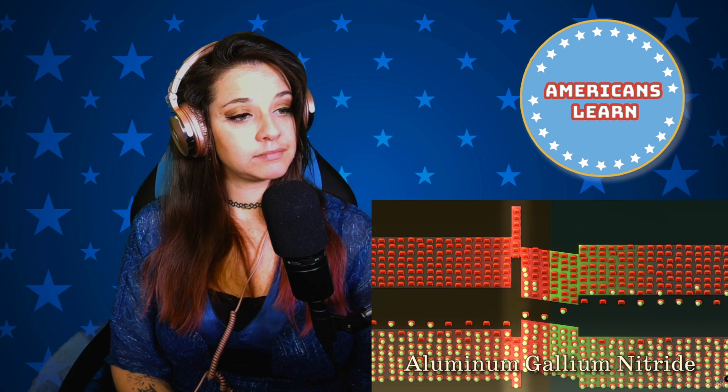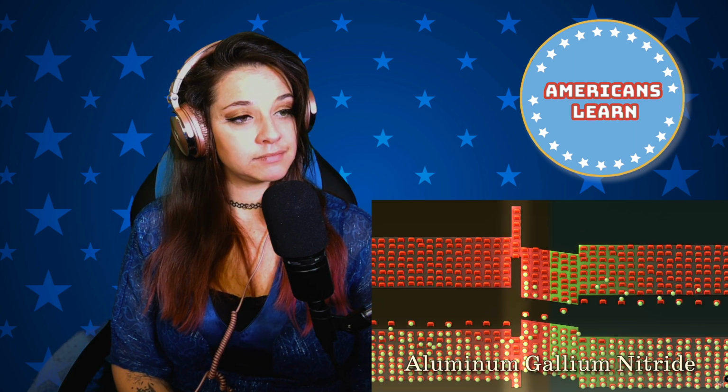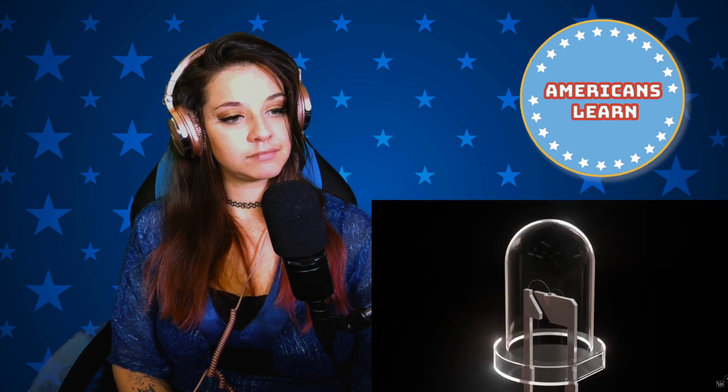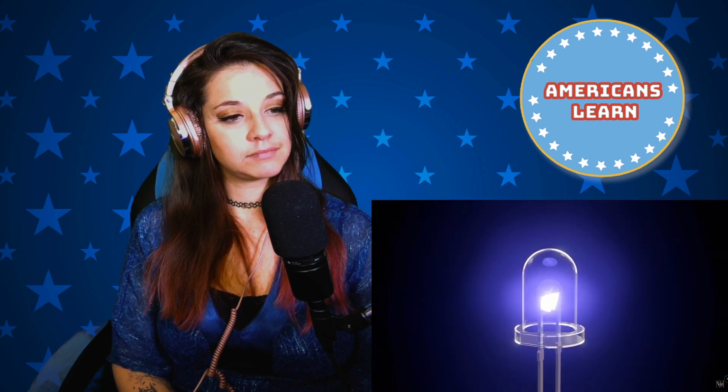Unfazed, within a few months, Nakamura had fixed this too, by creating the opposite of a well, a hill. He returned to his reactor one more time to make aluminum gallium nitride, a compound with a larger band gap that could block electrons from escaping the well once inside. The structure of the blue LED had become far more complex than anyone could have imagined. But it was complete. By 1992, Shuji Nakamura had this.